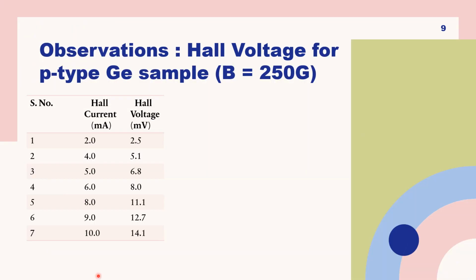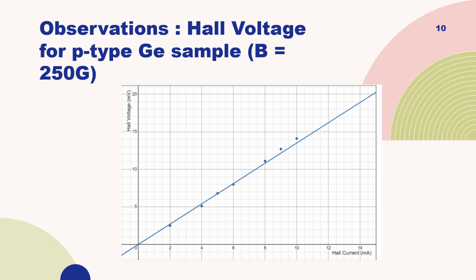So here are the observations for Hall voltage for a p-type germanium sample at the constant magnetic field B equal to 250 Gauss. We can see that the Hall voltage increases linearly with the Hall current, and so from this table we can deduce that the slope of the graph between Hall voltage and Hall current does not vary, which means the Hall coefficient is constant for the sample in this range of applied current. Here is the graph between the Hall voltage and Hall current for a p-type germanium sample, and we can see that it's fairly linear.